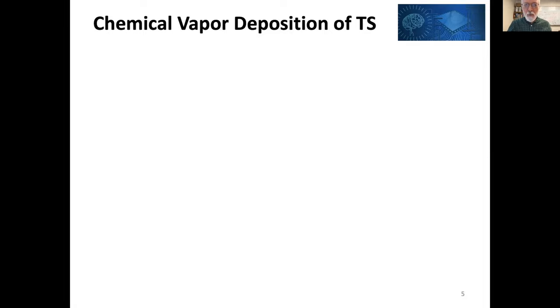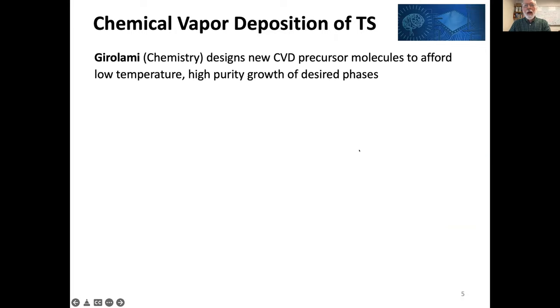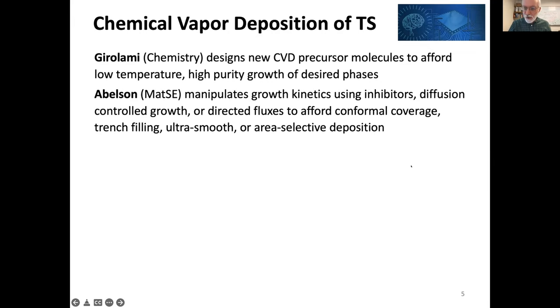I'd like now to speak about chemical vapor deposition of topological semi-metals. This is together with my colleague, Girolami. As I've mentioned, Girolami's great specialization is to design new molecules that give film growth at low temperature and give you high purity desired phases. And my role is to manipulate growth fluxes. We have over the years introduced the use of inhibitors and diffusion controlled growth with two reactants and directed fluxes. And what do we get? Conformal coverage, trench filling, ultra smooth films, on the sub nanoscale, and area selective deposition.